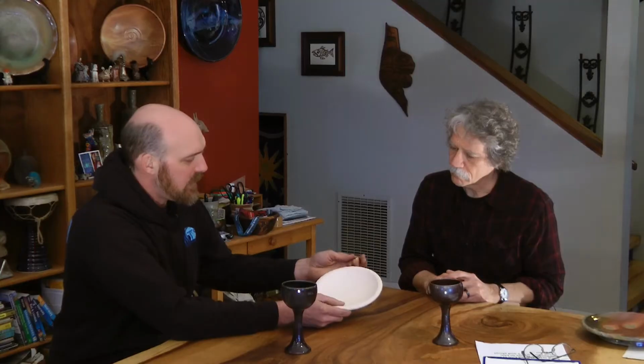The next step is to get it ready for wood firing. In the kiln, this plate sits in the kiln, and it has these things called wads, and wads are sacrificial clay balls, and you have to put these on every piece in the kiln, because as the wood ash is going through the kiln, it sticks to everything. It sticks to the pots, it sticks to the shelves and the posts, everything, the big stack that's in the kiln. And so if you don't have these sacrificial clay bumpers, the ash will stick to the pot and stick to the shelf, and they'll stick each other together. So if you break it off, let's pull this in. This might show us how exactly you're setting that up.